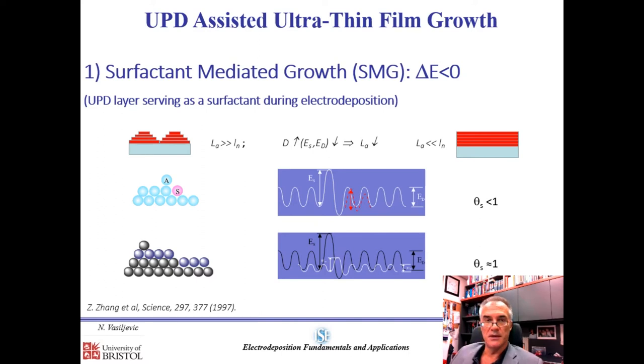And interestingly enough, that condition is fulfilled by most of the UPD metals if we are considering growth of some kind of a more noble metal. So basically what surfactants do, depending on whether we have them in a low coverage or high coverage regime, they mitigate the height of the Schwoebel barrier, which means they decrease the energy needed for an atom to step down.